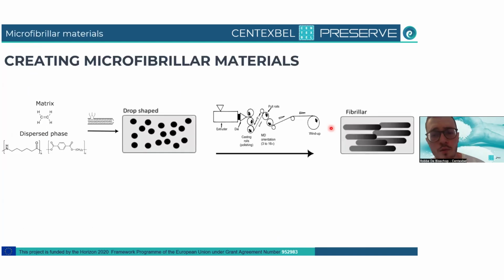And this is an overview of how this is going. So we have the matrix phase, the polyethylene, and then the dispersed phase. After compounding, we will get this morphology. If you look very closely with a SEM microscope, you will see a drop-shaped morphology of these materials. And what we try to do, via cast film extrusion, is to create fibrils of these droplets, so stretch these droplets out so they make very strong fibrils that are connected to the matrix by using compatibilizers to upgrade these materials.